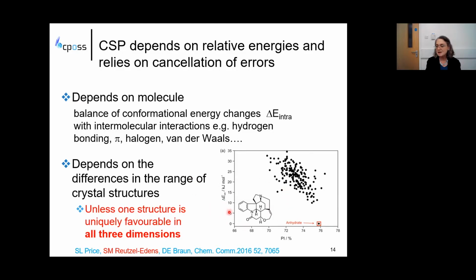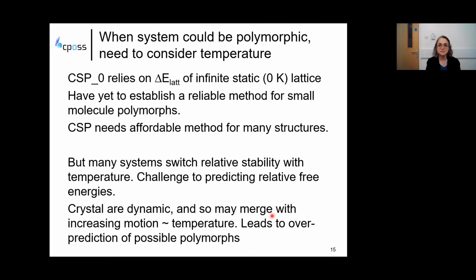Here's strychnine, and in that case, there's such a big energy gap between the known structure and all the others that you can be fairly confident it's not polymorphic, and you don't really need that energy gap that accurately. But we only get such a big energy gap when you've got such a shape of molecule and interactions that that structure is uniquely favorable in all 3 dimensions. Usually there isn't that degree of favorability in all dimensions, and you usually get quite a lot of potential structures.